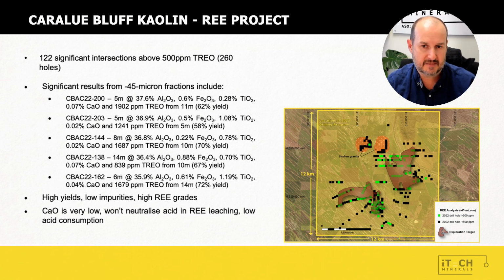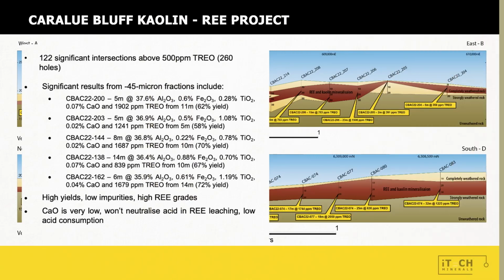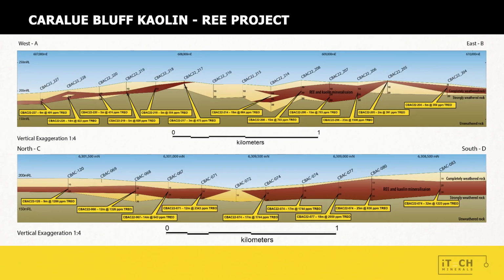It also decreased the amount of calcium that was present in the sample, which means that you don't get so much acid consuming or acid neutralising material. And that has real benefits for the cost of extracting the rare earths when you're processing it. The average depth to the top of this mineralisation is about 12 metres, so there's a low strip ratio, and the thickness varies between 5 and 12 metres.